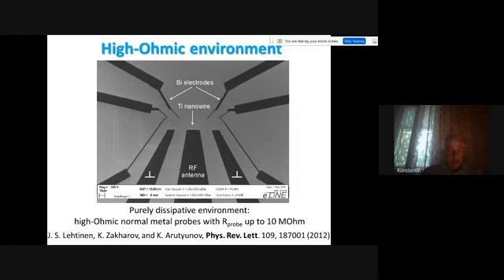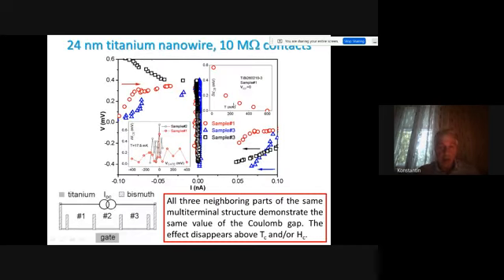And stabilizing the charge means that you have extremely good current biasing. And it is not sufficient just to put a good current source on top of your refrigerator. You should stabilize the current by the proximity of high ohmic electrodes. So in this generation of samples, we fabricated very narrow titanium nanowires with high ohmic bismuth electrodes. And some of the electrodes have resistance as high as 10 megaohm. And then we studied the IV characteristic of several subsequent parts of these titanium nanowires.